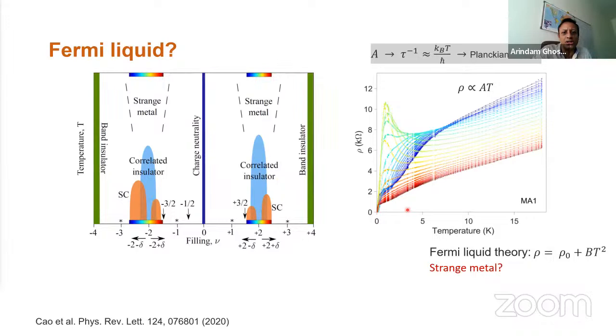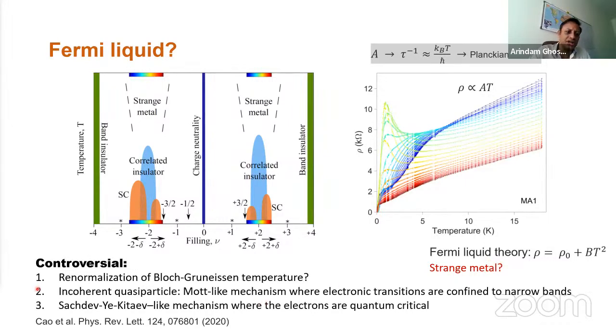And one of the questions was, okay, if it is a Mott insulator, then one of the key features of those insulating and superconducting phases in those high TC superconductors is the resistivity going proportional to temperature, which is very different from a Fermi liquid expectation where the resistivity is supposed to go as T square. And this is why it's called a strange metal. Okay, so the controversial aspect that emerged is: do we have a system where the Fermi liquid theory is breaking down, or do you have a system where these are quantum critical systems?